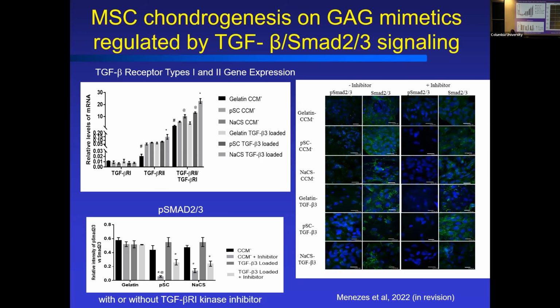We can look more carefully even at some of the other signaling associated with the binding of those receptors, which is the SMAD2/3 and phosphorylated SMAD2/3. We find that if you have high expression of that phosphorylated SMAD2/3, and you inhibit one of those receptors, only on those GAG mimetics do you get this silencing down or lowering of that phosphorylated SMAD2/3. So it really shows that there's a direct link there. Sequestering TGF beta on those GAG mimetics promotes the TGF beta receptor interaction and then promotes the SMAD2/3 signaling that then leads to chondrogenesis.